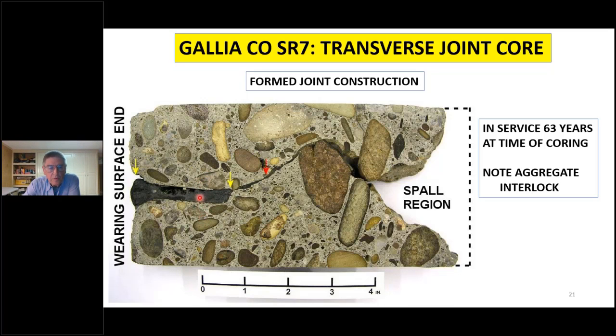The form joint forms a rougher surface than you get with the saw cut, obviously. So you get the benefit of the attachment there, plus the flare at the top to eliminate the breaking off of the corners of the joint. And the distance here from the bottom of the form joint down to this point was filled with a hot melt material.